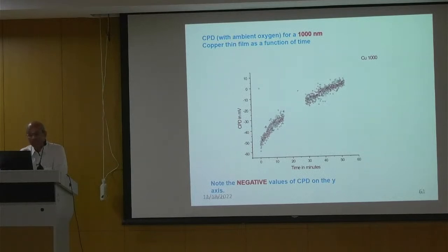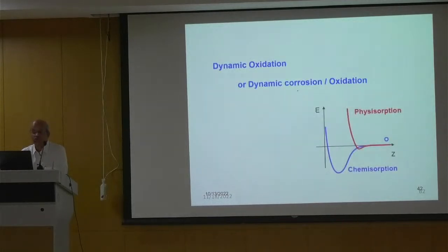is known, and we are able to follow the oxidation kinetics, because these are not very fast, up to almost about 60 minutes and beyond. Is there any other technique which can give you this type of experiments without really touching the surface? I would like to say probably there is no other technique. So this is one important point about Kelvin probe, and whether it is dynamic oxidation or dynamic corrosion,